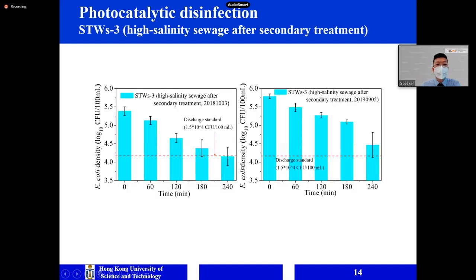But the situation gets worse in the following two types of sewage. For the high salinity sewage after secondary treatment, we can see that it took 240 minutes to meet the discharge standard. And in one sewage sample collected in 2019, even after 240 minutes, the treated sewage cannot meet the discharge standard.